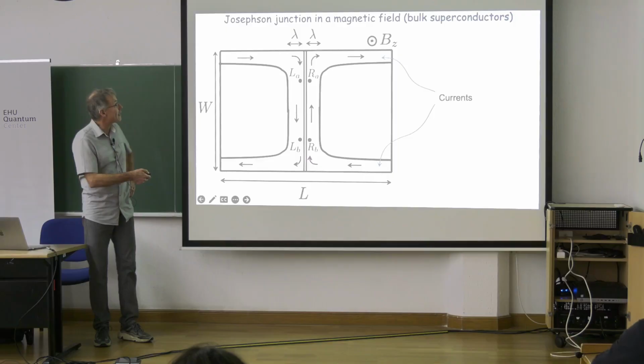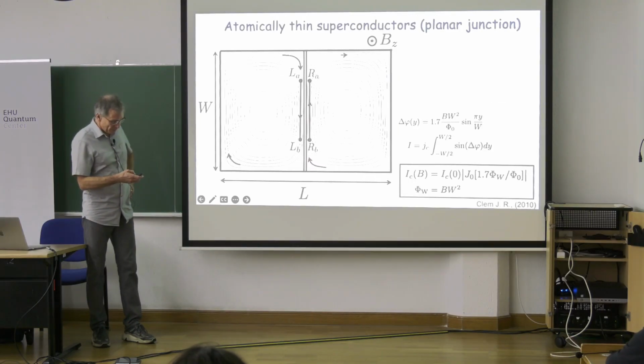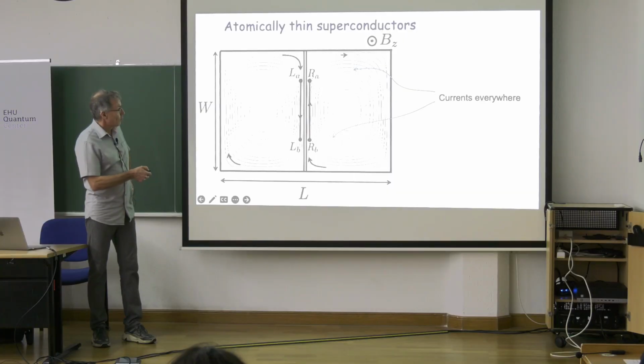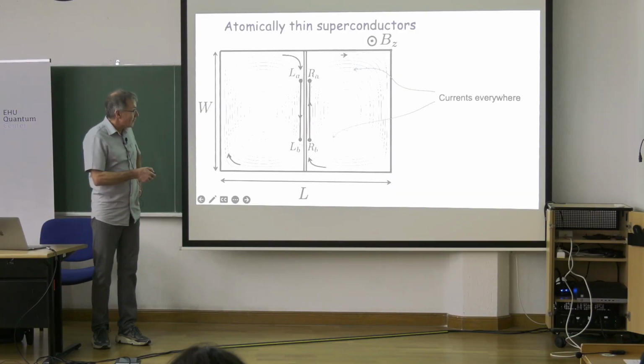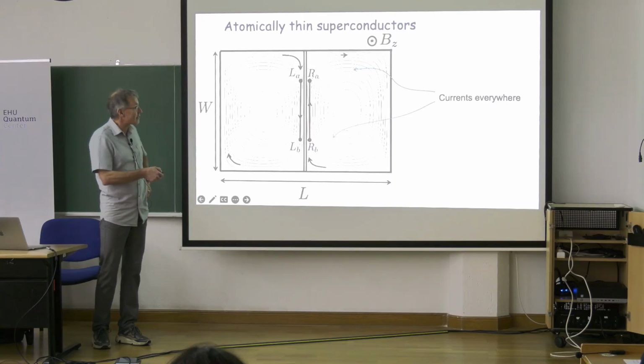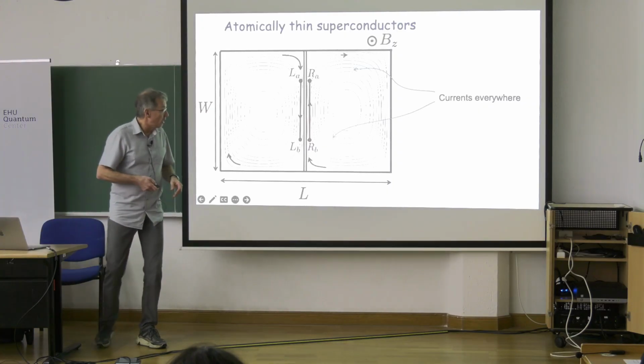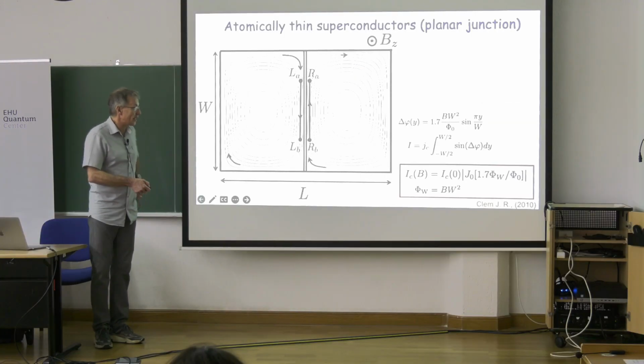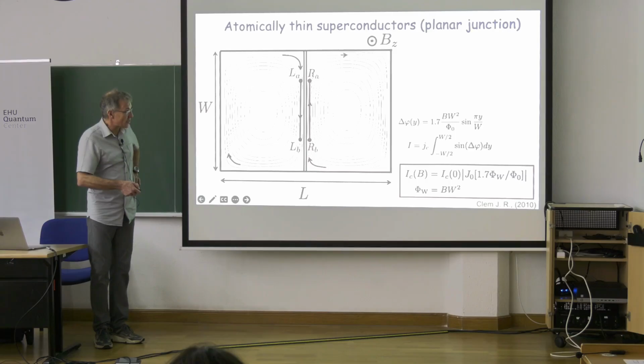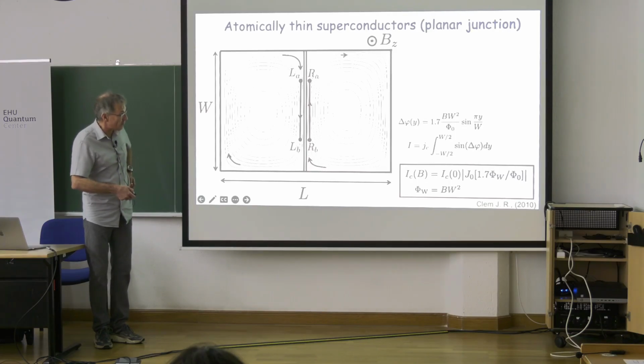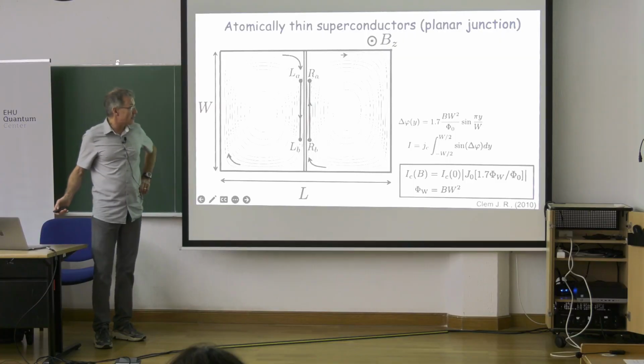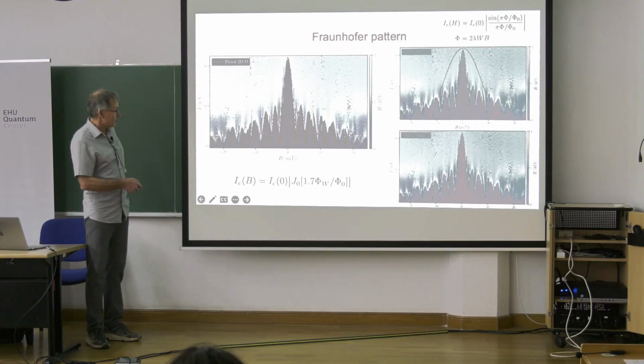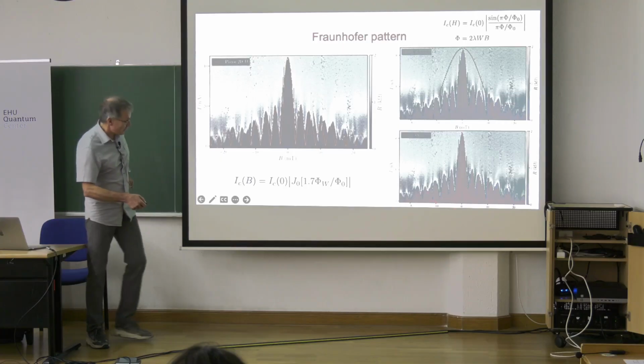Now, for an atomically thin superconductor, we cannot use this formula because the field is not expelled. Field is everywhere. Currents are flowing everywhere, so we should do a better job. And we can do it. Instead of sine of flux over flux, there would be a Bessel function. And this actually has quite a different shape. So this orange is the formula for a planar junction. And this red, well, the different, oh, can one see it?